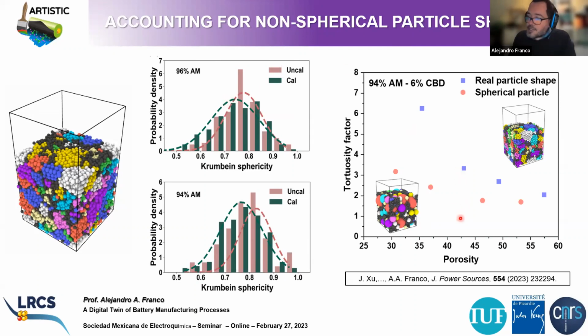And in this graph here, you see a comparison of the tortuosity factor of different electrodes that have been simulated by using this framework as a function of the porosity for a given formulation. And here we compare the case of the model accounting for spherical particles, these are the circles here, with a model where we consider non-spherical particles. And you see that for the non-spherical particle case, the calculated tortuosity factors of the calculated electrode microstructures are systematically higher than the tortuosity factors corresponding to the electrode microstructures calculated with the spherical approach. And the reason is that when you have non-spherical particles that are actually deformable, when you compress the electrode it becomes more compact, right? And if the electrode becomes more compact, then the pore network inside the electrode is going to be more and more tortuous, right? And this explains why the tortuosity factors are higher in the non-spherical case versus the spherical one.